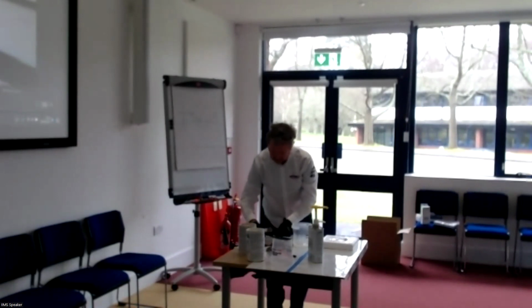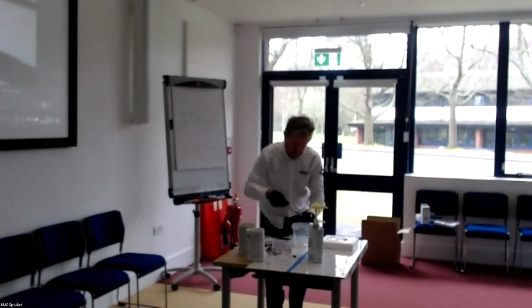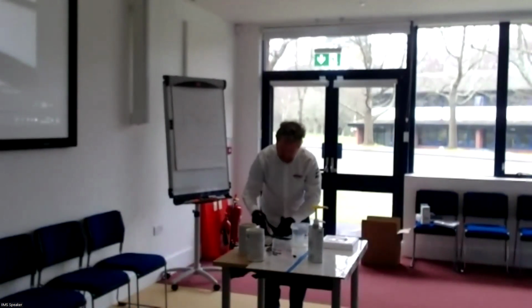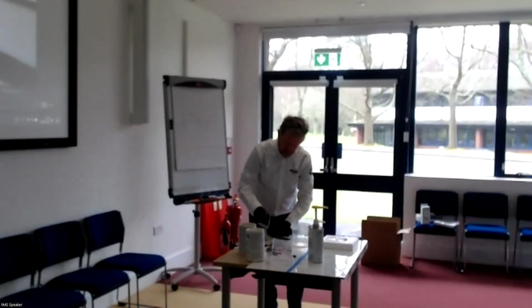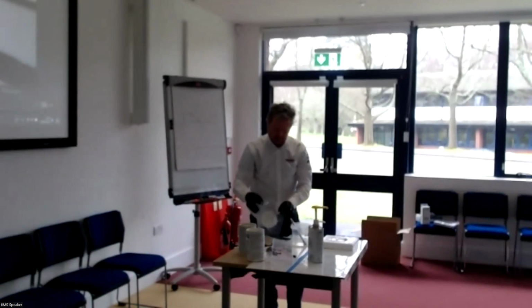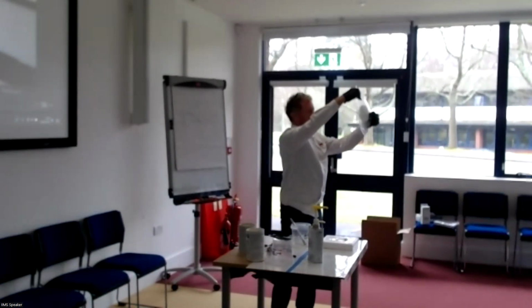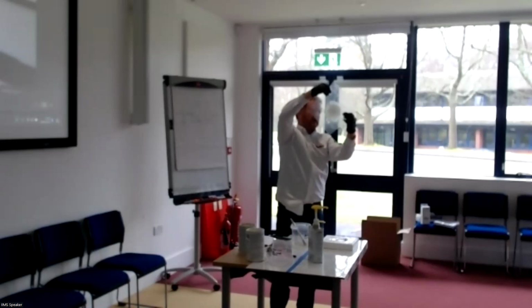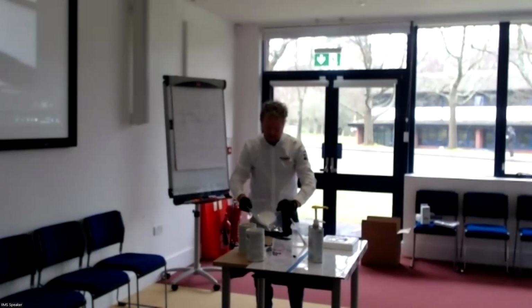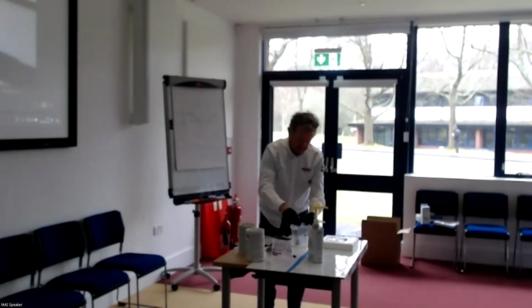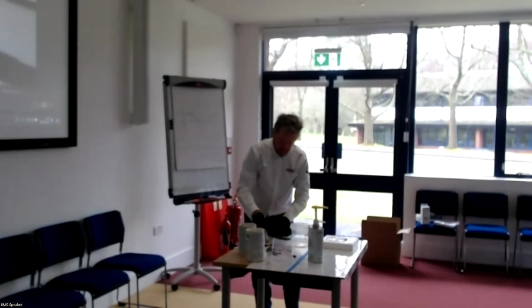This is the kind of look that you're going for as well. This kind of translucent epoxy look with very little air. The beauty of doing this onto a piece of polythene is that I can use quite a degree of force to consolidate the fabric, and you can see it's actually starting to become like a homogeneous, what I would call epoxy colour. That's slightly translucent green.